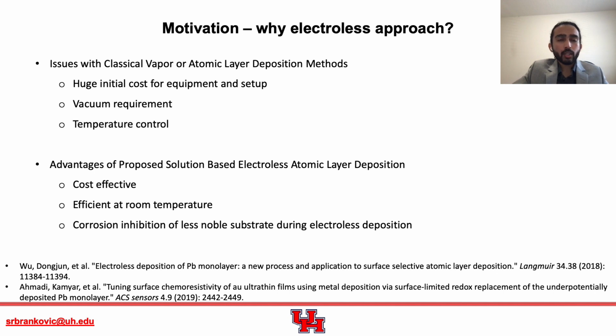With these factors in mind, our research group has previously studied electroless deposition, as shown in these two publications here. The conclusion of that previous work is that there are certain advantages of solution-based electroless atomic layer deposition over conventional methods. They are highly cost effective. The only thing we need is an inert or oxygen-free atmosphere. They are efficient at room temperature, and as in one of the projects I'm going to talk about today, we have demonstrated that we can show corrosion inhibition of less noble substrate during electroless deposition, which is not easy to manage even in the case of classical electroplating methods.